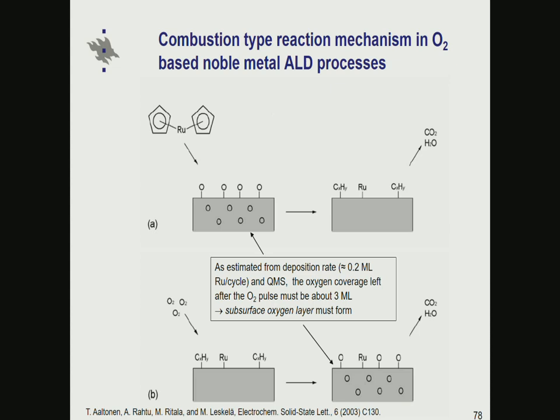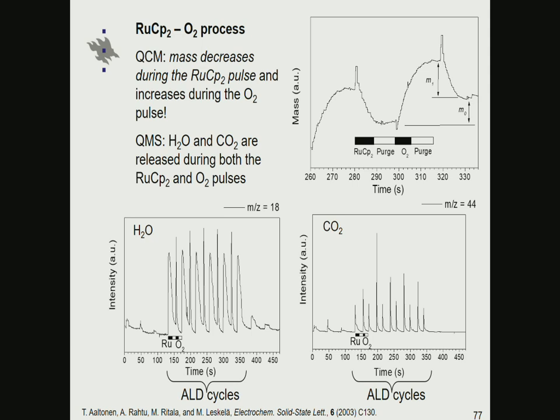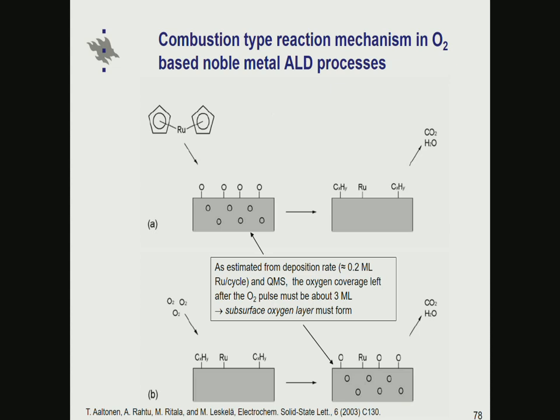By carefully using this data from mass spec and quartz crystal microbalance, we came to this kind of explanation: after the oxygen pulse in the process, we have atomic oxygen on the surface, but also in the subsurface regime of the ruthenium film. Now when the ruthenium precursor comes, all these atomic oxygens react with ligands, producing CO2 and water, as we saw with the mass spec, coming out during both pulses, leaving still some hydrocarbon fragments and adding the ruthenium metal. And then during the oxygen pulse, oxygen molecules dissociate, forming atomic oxygen, which combusts the rest of the hydrocarbons away, and then recharges the atomic oxygen on the surface and in the subsurface regime.